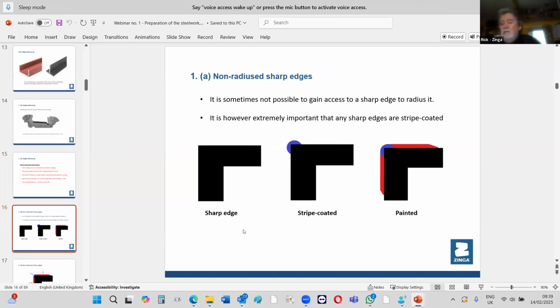Okay, there are sometimes situations where it's impossible to get in. We have guys that have been called in to refurbish parts of a refinery or a big sugar processing plant, and the beams are very hard to access. I said, okay, do your best on the sharp edge. If you can blast along one side of the edge, and then blast along the other side of the edge, and then stripe coat it with a brush, and build it up. As Abe was saying earlier, you use a brush to stripe coat it and build it up. And then when you put your coating on, you'll see it's consistent again.